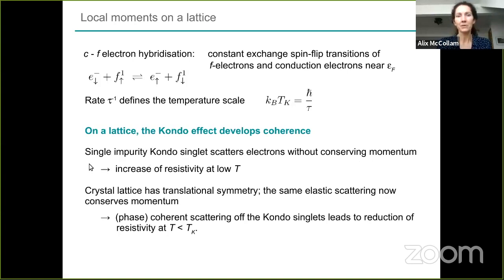So the single impurity will scatter the electrons elastically, but it's not conserving momentum. And this is what gives you an increase in the resistivity for this single impurity system. When you're on the lattice, you have the translational symmetry. So you still have the elastic scattering, but now it's momentum conserving, and you get a reduction of the resistivity once you go below this Kondo temperature.